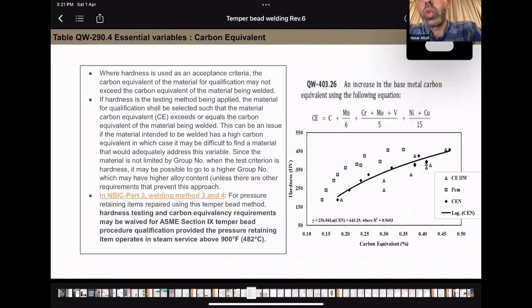Carbon equivalent. This is also an essential variable when hardness is specified. So for the carbon equivalent, we don't refer to any normal chemical composition specified in ASME Section II-B, for example. No, you need to have an actual composition of all elements specified in the carbon equivalent equation. You have different carbon equivalent formulas. All of them are accepted, but you need the actual composition of this.